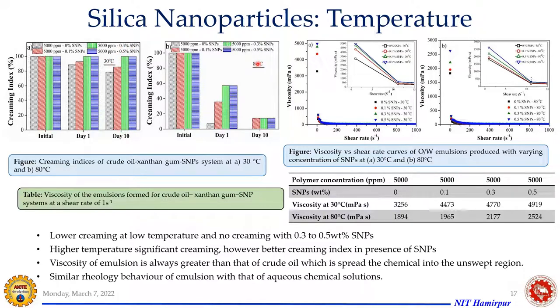The same condition was exposed to a high temperature of 80 degrees centigrade, because we have just taken a tentative temperature, as we wanted to compare how oil recovery will be affected at high temperature. So you can see here, initially, as usual, the emulsification was pretty high, so no creaming at all. Creaming index was 100%. And when we reach day 10, the solution which had no nanoparticles destabilized. So 100% creaming was there, and that's why its creaming index went to zero. Whereas at higher temperature with nanoparticles, though there is severe creaming, still some emulsion was there, which shows that it has a somewhat better profile than in the absence of nanoparticles, where it is totally zero.